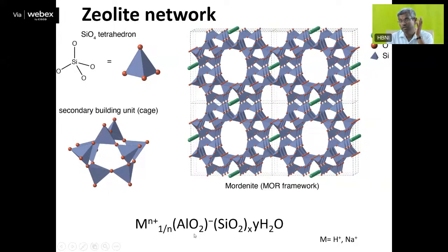That is why a zeolite can be used for ion exchange applications. But one should be careful which ion is exchanged, whether the sodium ion is getting exchanged or whether it is going and sitting in the pores. In the pores we also have water molecules, and some of the linkages, maybe OH linkages, may be there, so it can get exchanged for protons also.